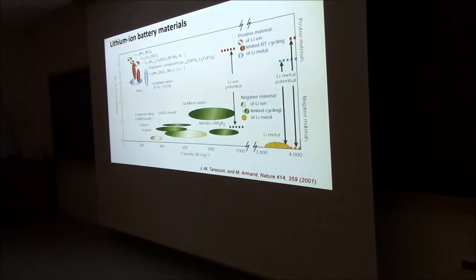However, a lot of the research is also on changing the graphite for something else, which is, let's say, of better performance. And what you will see is a lot of the research is focusing here on lithium metal, pure lithium metal, where the capacity is about a factor of 10 higher. You have to put in only a little bit to have the same amount of capacity as nowadays, so it's not about putting more in, but about smaller volumes. But it causes problems. Lithium metal, I will show you in a minute, is not stable, so that's what people are trying to improve.